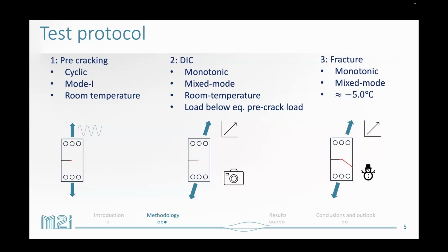And finally, we do the fracture phase, which is also in mixed mode, so also depending on the load angle, but we do this at -5 degrees Celsius. For this, we cool down both the specimen and the grips in a fridge to approximately -40. Then we transfer everything to the hydraulic machine, wait until it's at approximately -5 by monitoring it with thermocouples, and then we do the fracture test. Due to these low temperatures you have condensation on your surface, and that's the reason we cannot use DIC anymore in this phase. That's why we split it in these two aspects.